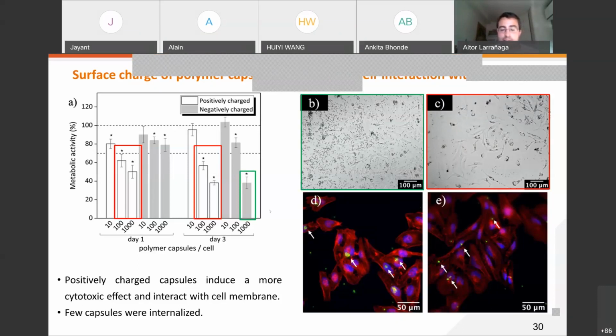Well, when we checked the internalization of our polymer capsules, we found that very few capsules were internalized by cells, irrespective of the positive or negative surface charge. So here we believe that our capsules will mainly scavenge these reactive oxygen species that will be produced in the extracellular environment, and not so much the reactive oxygen species that are produced inside the cells.